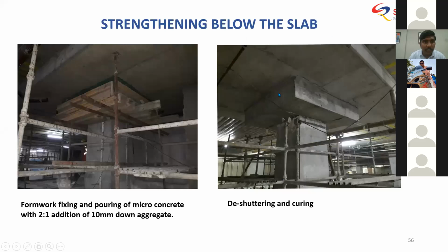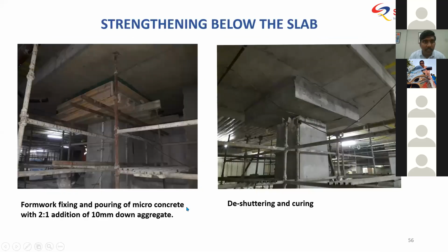All right, oh yeah, I missed out one point. It was done using microconcrete. Microconcrete has 10 mm down aggregate, as I told earlier. Addition of 10 mm down aggregate. So you increase the amount of aggregate in this by adding extra.